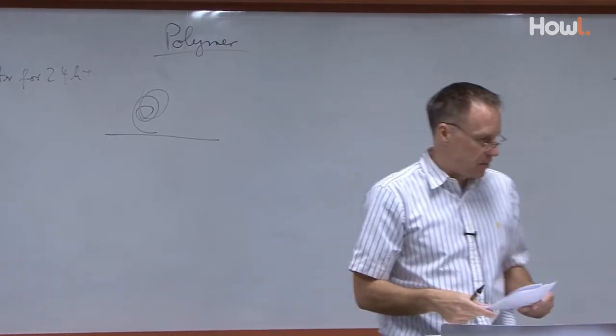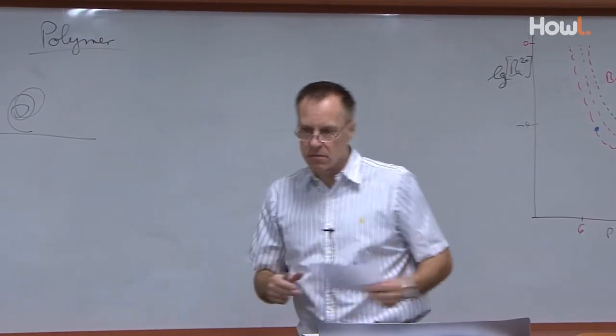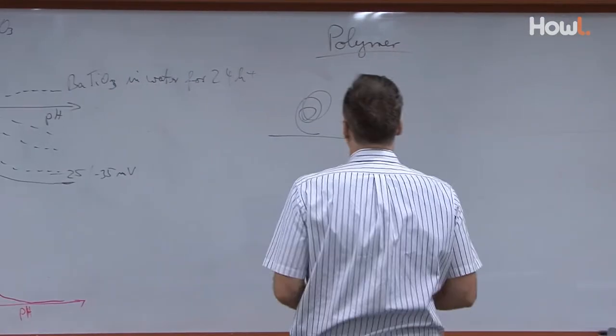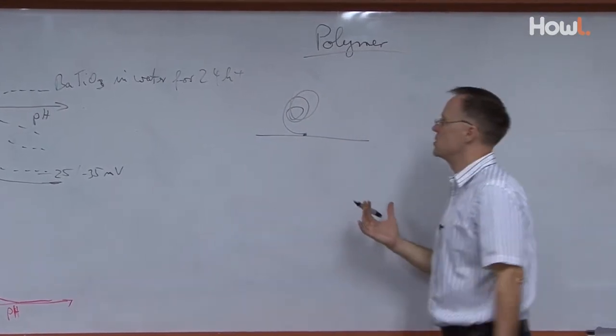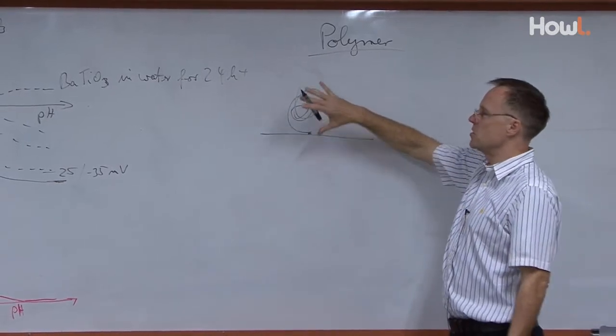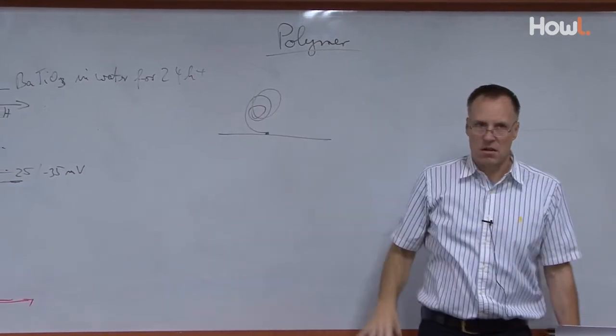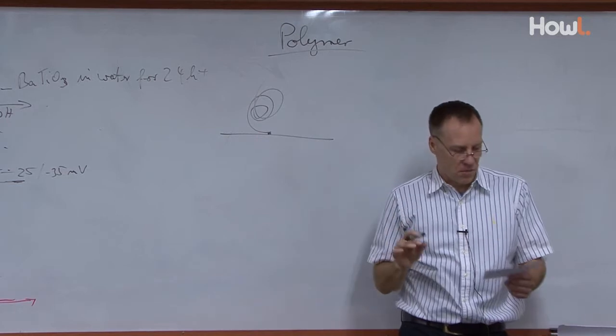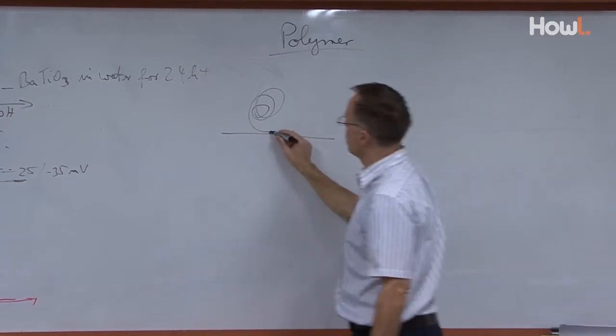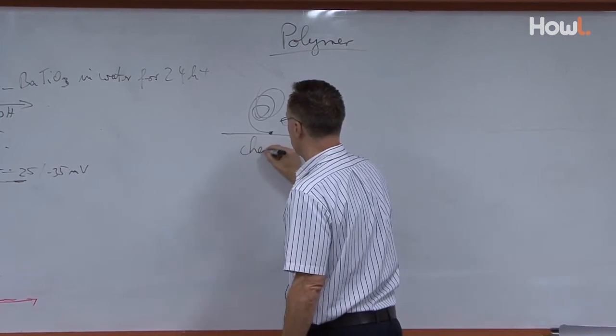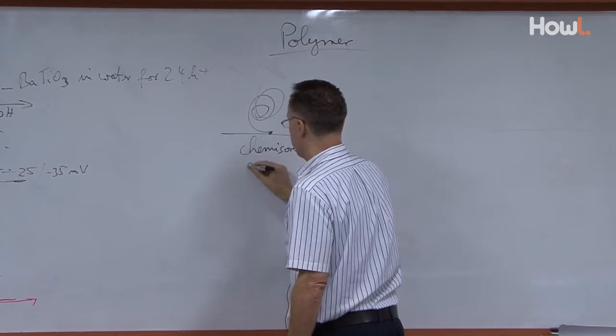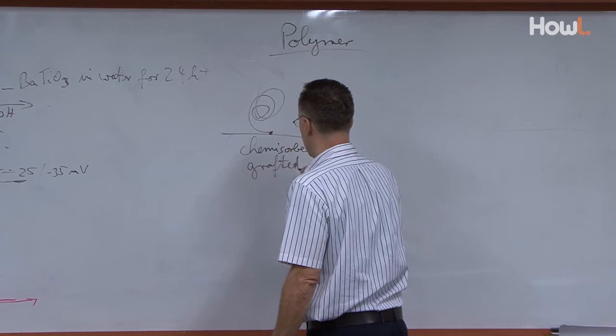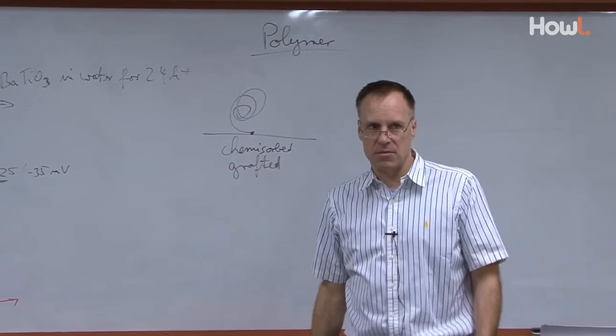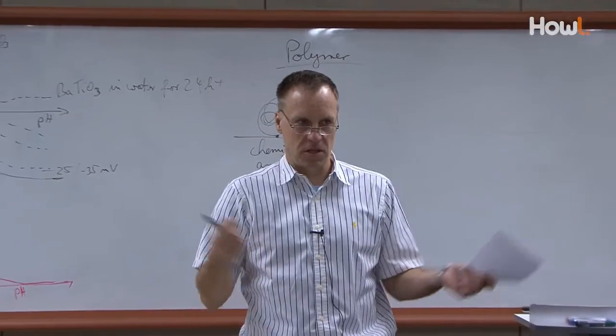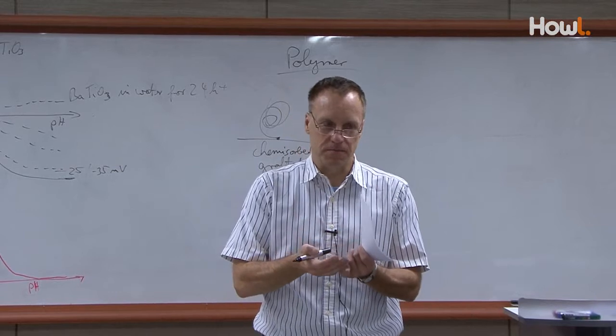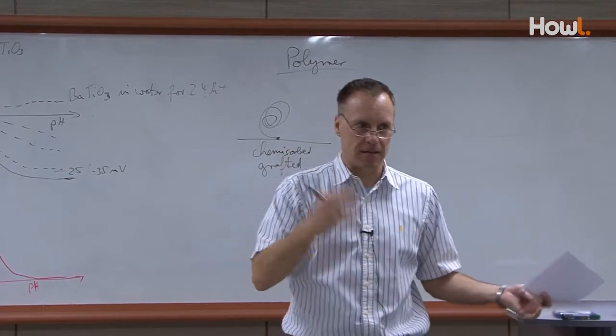And there are then basically possibilities how these things can adsorb on the surface. And the first thing would be just anchoring basically at the end here at one part of the chain and then having a coil. And that's actually pretty interesting because now you can calculate the size of such a chain just by statistics. There are several ways of doing that, and we come later on to this. So this system here where you have an anchoring at one point is called a chemisorbed or grafted polymer. Yeah? So grafted system. The grafting, of course, means if you do chemistry, you have to pay attention to the conditions. Chemistry, basically, if you work in water, certain chemicals don't react necessarily in this spot. So if you work in organics, again, then you can do that.